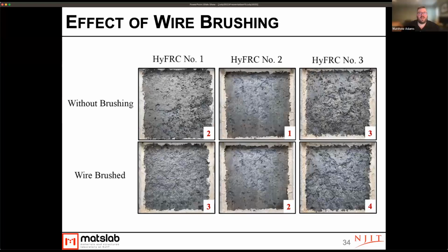But one thing we noticed with the systems that had fibers is that the fibers tended to hold material on the surface. And so the test method doesn't actually request that you brush the surface or clean the surface off. You're just supposed to sort of rinse the waste material off and then look at the surface. However, that doesn't really give you a full picture of the damage that you're seeing in those slabs. And so we recommend that if you are testing these fiber reinforced systems in salt scaling, that you do a light wire brushing of the surface to try to clean off some of those materials that are stuck on with the fibers, because they may actually be a trip or a skid hazard, particularly for walkers, if they're stuck on there but not really tightly held on there.